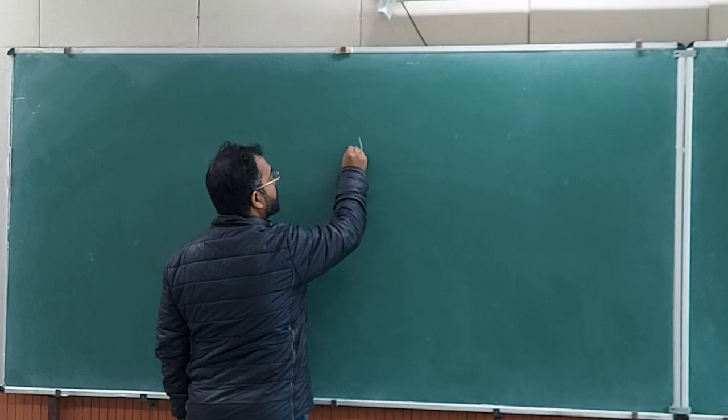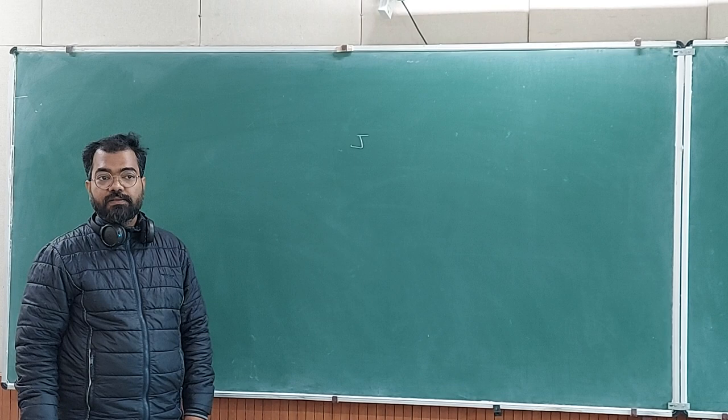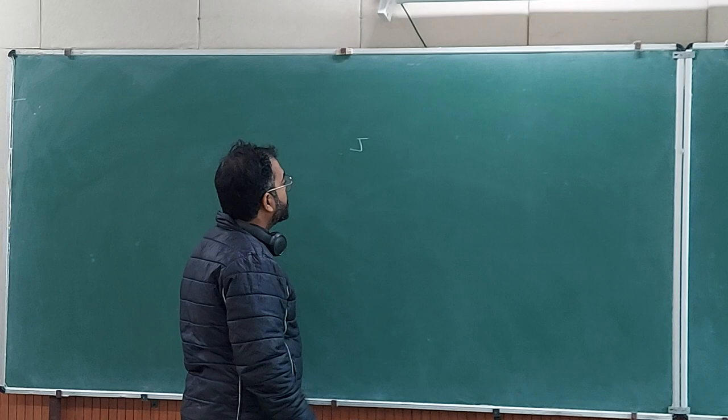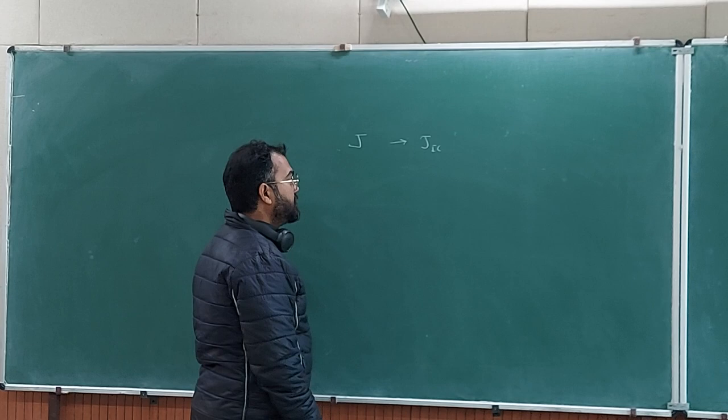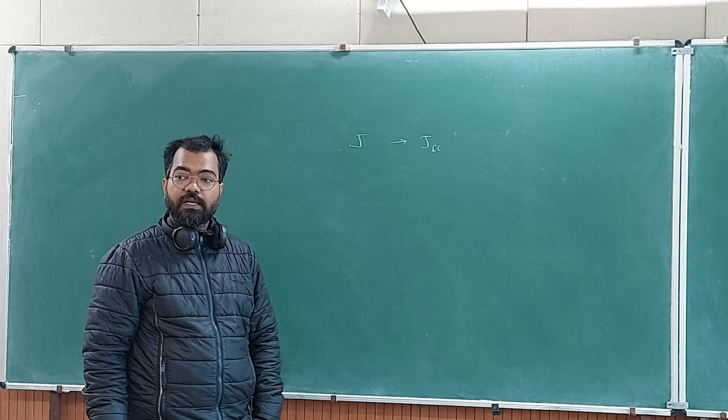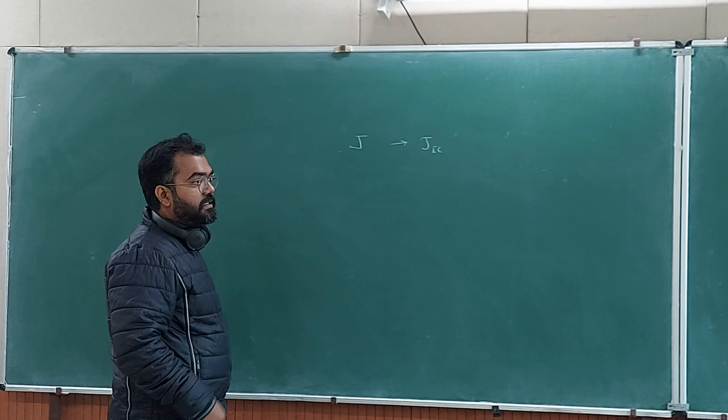Now we want to know, how do we calculate J experimentally? Based on the J integral, there are many standards, and you can find the initiation fracture toughness from this, which is J1C. But because the J integral is applied to ductile materials, you don't have a PQ kind of thing like you do in K. So in J integral testing, the load displacement curve will be very long.